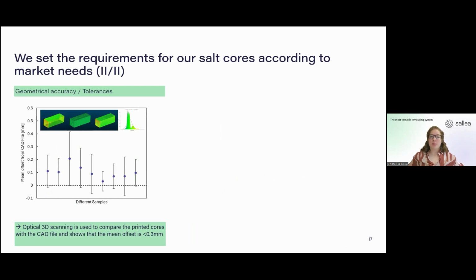Now, what is also very important to look at, especially for our customers, is the geometrical accuracy and the tolerances. And for that, at the moment, we are working with optical 3D scanning. What we have done is that we compared these printed salt cores with the CAD file. And what you can see on the images that I show on top of the graph is how it looks. You see in green, it fits very well to the CAD, and where it's a bit red, it's slightly different from the CAD file.